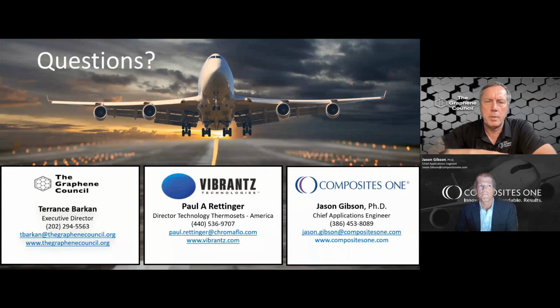Not in this particular study, but there is data, and that's kind of what we do with the Graphene Council, is we inventory both research reports and commercial applications. Basically, any of the resin systems or chemistries, graphene has been compatible. We should think, again, graphene is 100% carbon. And it has a lot more to do with which system it goes into, the rheology of it, and how you're doing the dispersing. It has to do with the individual particle size. We have to remember that a single atomic layer of graphene is 1/3 of 1 nanometer in vertical height, or z-axis, and it could be submicron to several micron across in lateral size.